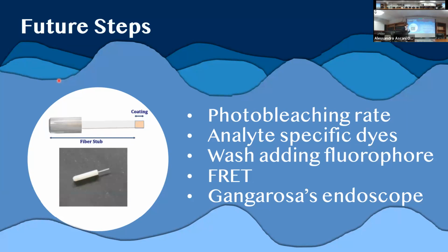If we want to retain as much fluorophore as possible in these particles, we should consider replacing this surrounding liquid with ethanol rich in fluorescein, essentially, so that there is no chemical gradient created and the fluorophore will not leach out while we don't have a shell.